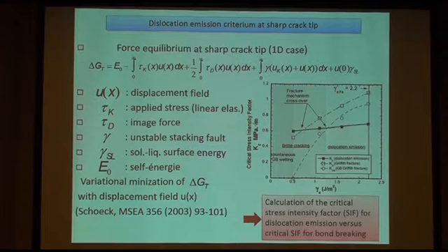One of the criteria that we can use is to compare the dislocation emission process, which can be described by just the force field of the crack, the square root of r profile for stress, use this force field and also implement the unstable stacking fault that DFT people start to produce now in many systems, and also incorporate the surface effects with dependence on solid-liquid surface energy.